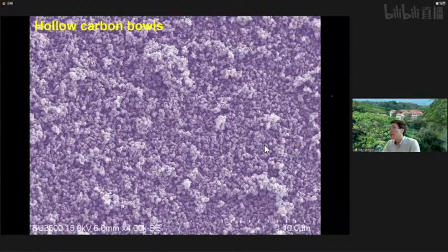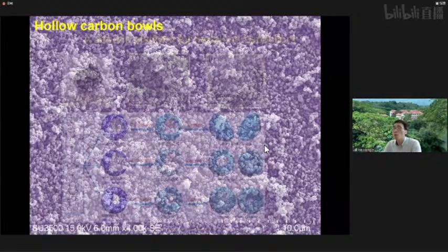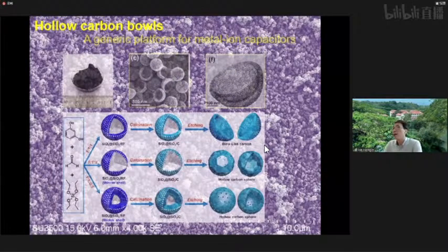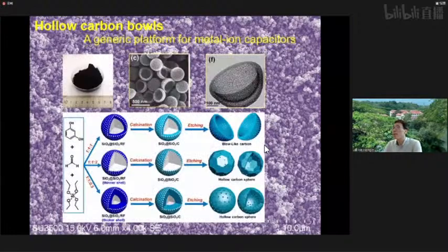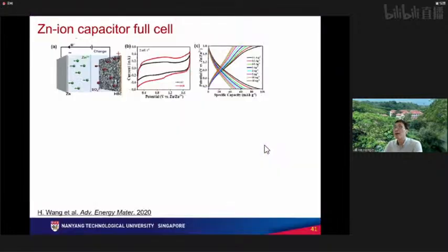This work is in collaboration with my previous postdoc Wang Huangwen in Wuhan. They fabricated, at very high yield, this kind of hollow bowl-like carbon with a lot of mesopores on the surfaces. They can tune the morphology by tuning the ratio of the precursors. Of course, this is a very well-established process in the literature. So we just apply this hollow bowl-like carbon as the cathode for the zinc-ion capacitors.